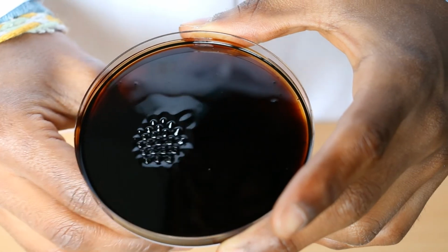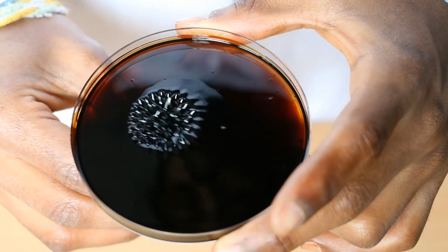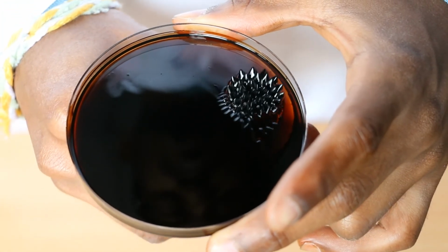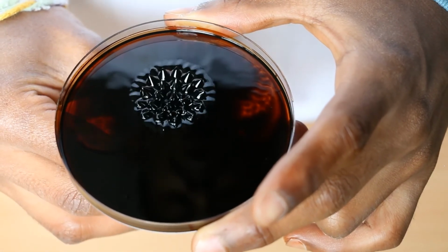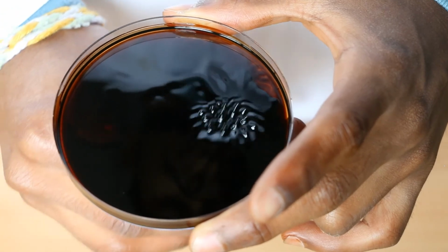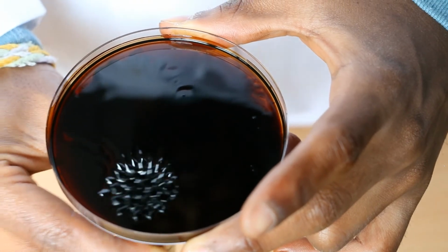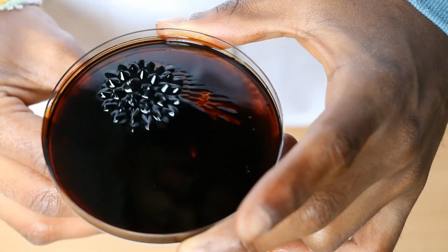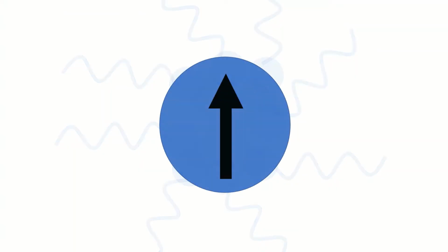Ferrofluids work because the magnetic particles are so small. Normally, magnetite, being made of iron, is ferromagnetic, and as a result can be attracted or repelled depending on the applied field. Ferrofluids, on the other hand, are always attracted to the applied field, like a paramagnet. The magnetite in a ferrofluid is less than 10 nanometers in radius. To put this in perspective, visible light's wavelength is between 450 and 700 nanometers, and a human hair is several thousand nanometers in diameter. At this tiny size, room temperature provides enough energy to keep the magnetic moments constantly flipping between north and south in the magnetite.